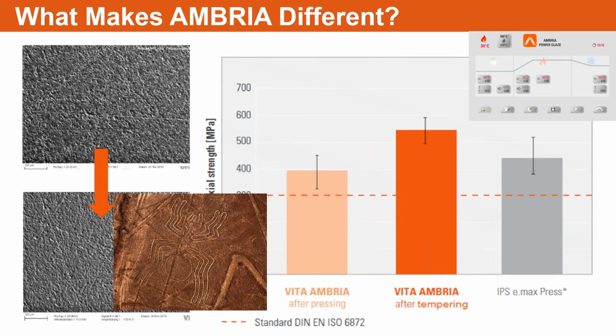Now, the other thing is that we recommend that after you press it and you cut the screws off, and before you get going, you place that restoration back in the furnace and do what we call a tempering or a power glaze. It's at a lower temperature than the press, but it will help smooth out the surface after it's been pressed, all those peaks and valleys of your surface microscopically, and the smoother your surface is, the stronger your material is. So we can elevate our material strength from an average of 400 and go up almost 550, and it has what we call a very small deviation. So we can increase the strength by doing this tempering or power glaze. It's a simple process. It's just an extra firing, but no problem.